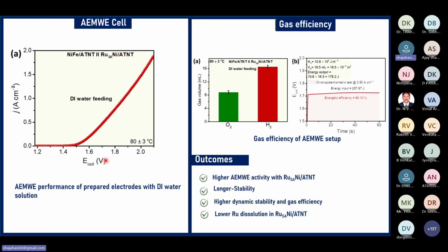With the pure water also, our gas efficiency increased from 63 to 69.10% when we use pure water as electrolyte. And when we use DI water, we also got better performance. Even at 2 volts, we got more than 1.5. So this is also good. So that means the nickel Fe and ruthenium single atom nickel based electrolyzer shows better performance in the case of both KOH feeding condition and DI water feeding condition.